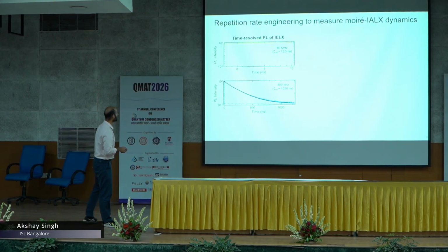What we think is happening is that we are saturating the interlayer excitons. Let me explain how we're doing that. If I probe the PL of this interlayer exciton within 10 nanoseconds, it doesn't decay. But if I change the repetition rate of the laser, I see that the interlayer exciton is able to decay with a period of about 200 nanoseconds.